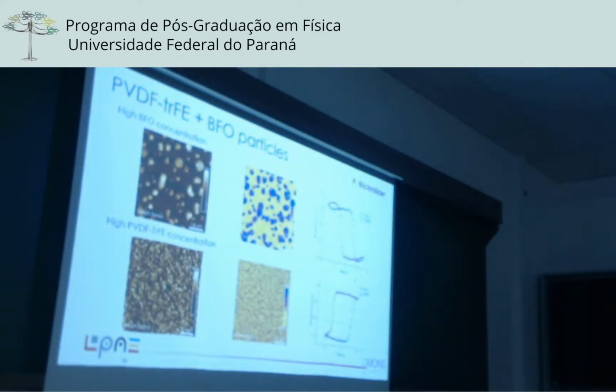Then we go for AFM to measure the electrical properties. So this is the topography. This is the phase. You can see some BFO here, and we have this PFM hysteresis loop, so we know that we are sure, and you can start to measure the properties of these piezoelectric nanoparticles inside the system.